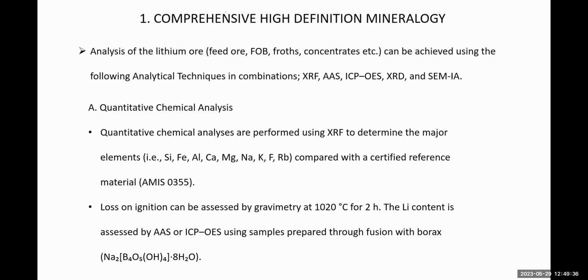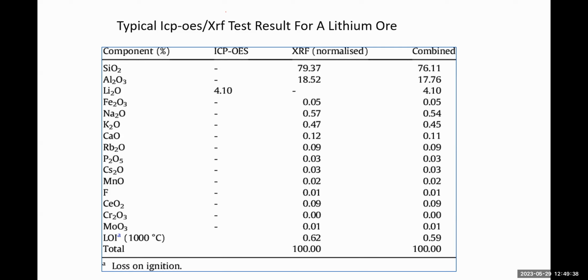So next slide. This is a result of test work that was done for a lithium material. You can see the elemental constituents, and you can see here two instruments were used, ICP and XRF. In this case, the XRF couldn't detect lithium because XRF does not have the capacity to detect elements of low atomic number.